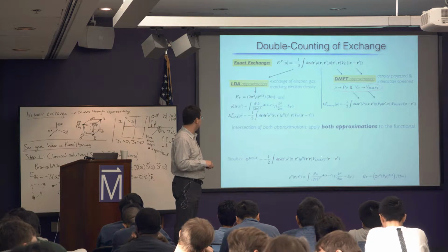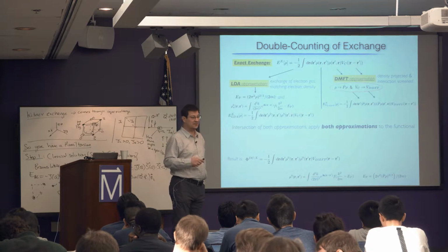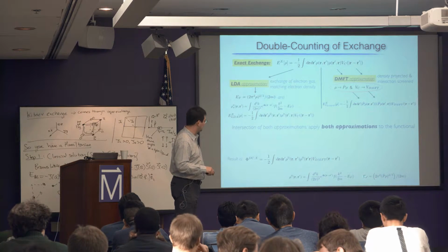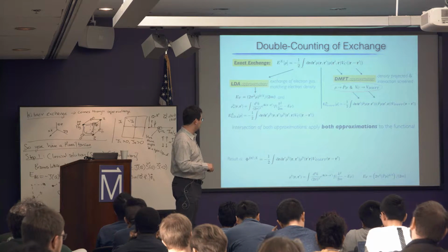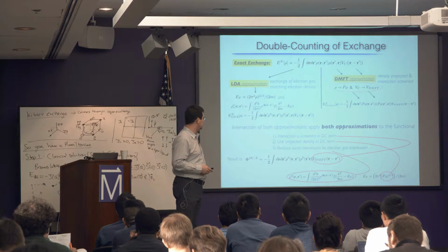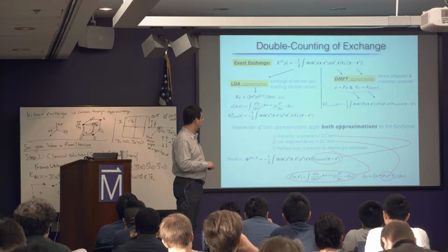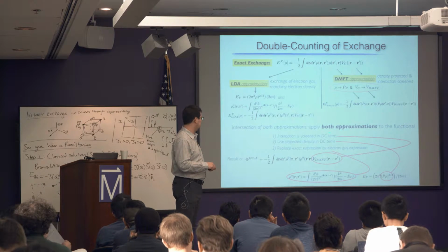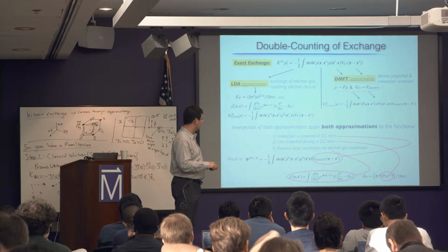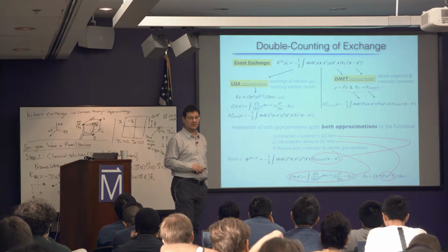And then at the same time, rho 0 has to be calculated from the projected charge density, isn't it? Because that's what DMFT requires. So therefore, you need the projected charge density with which you calculate the Fermi energy. Then this defines your rho 0. Once you have rho 0, you have to take into account V DMFT, and basically, this is the recipe. So in summary, the interaction is screened in the double counting term, like DMFT suggests. Then we need to use the projected density in the double counting term, and we need to replace the exact expression by the electron gas expression. Okay?